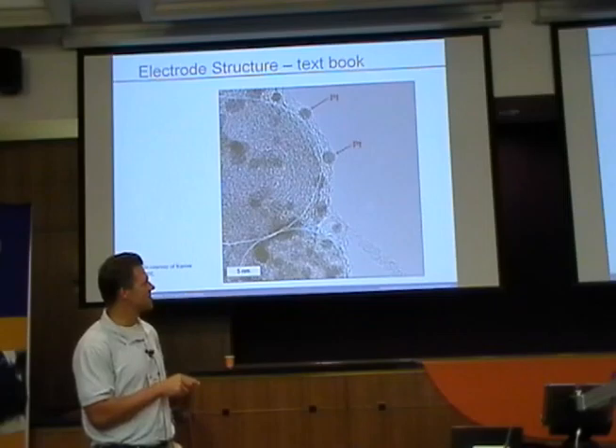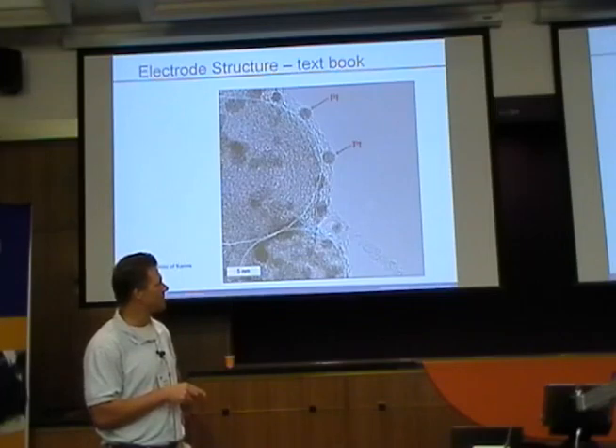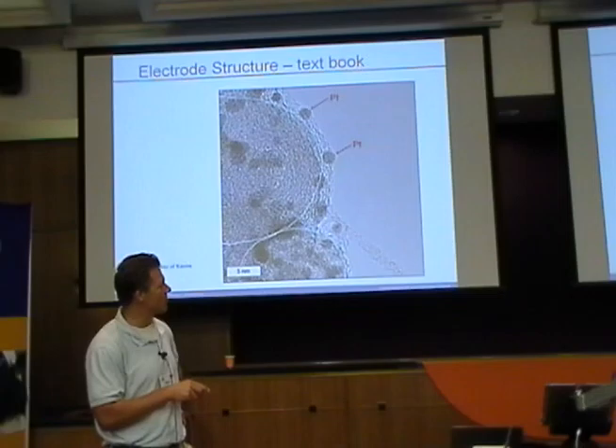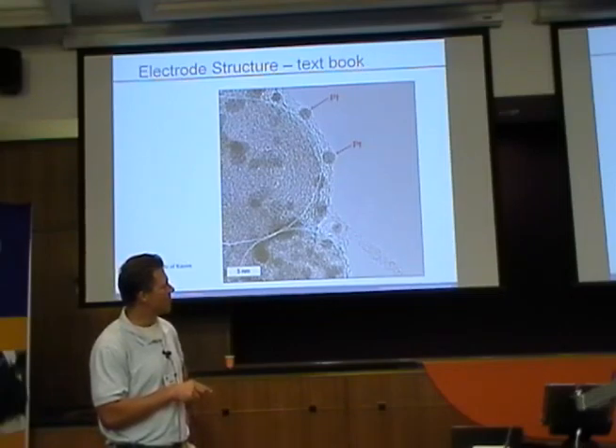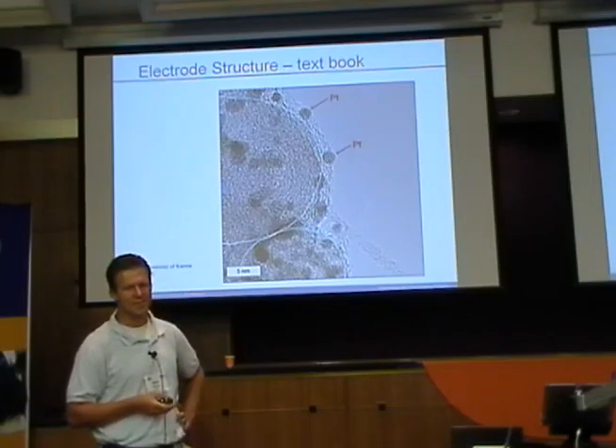And what I have here is platinum on carbon. So these blue outlines that Karen Moore at Oak Ridge put on these micrographs show basically, you can see these turbostratic sheets of graphene that are basically the carbon particle. And then you see the platinum on top of it. And then you see this thin skin of ionomer. And so this is Nafion, and that's an ion conducting polymer.